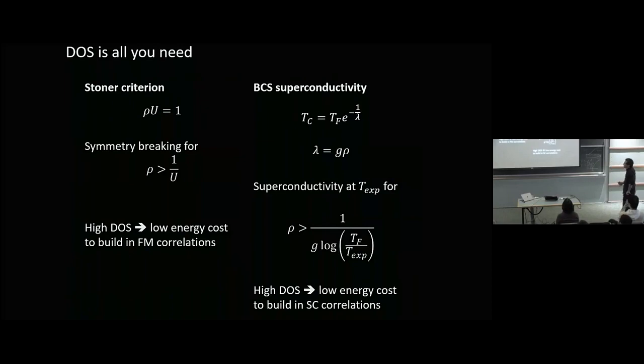This basically follows from simple, textbook physics of metals. For magnets, you have the Stoner criterion, which basically says, whatever your Coulomb repulsion is, if you can get your density of states high enough, you'll have some magnetic transition. BCS superconductivity, also, if you increase density of states enough, you decrease the energy cost of building some superconducting correlations into your ground state. And indeed, this is what's played out in a pretty dramatic fashion in these systems.